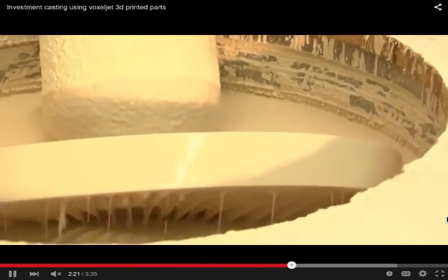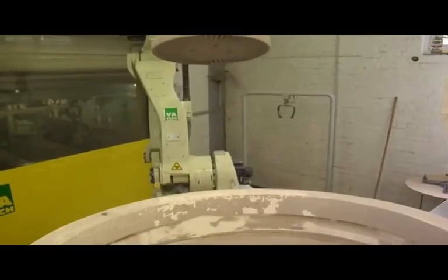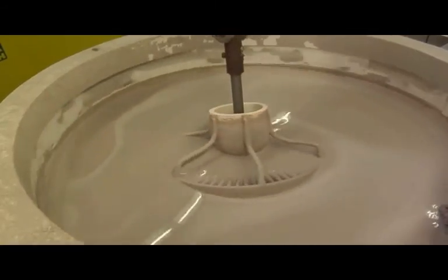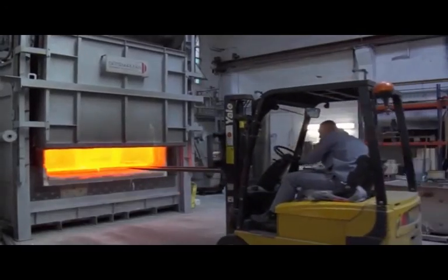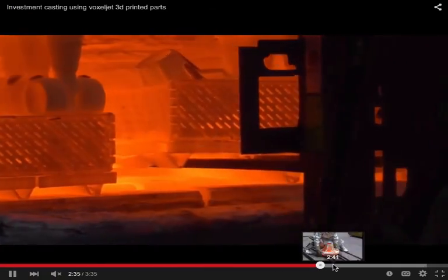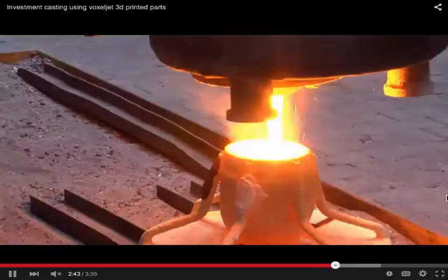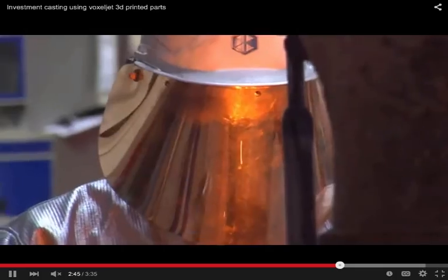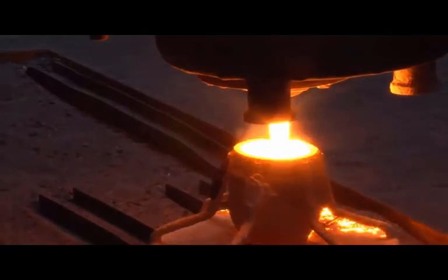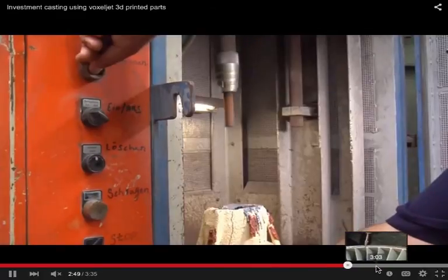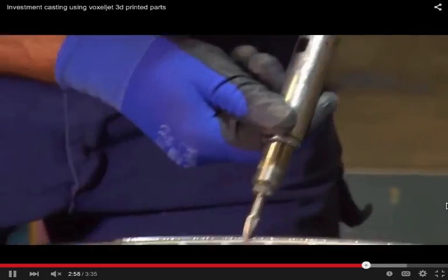They'll do it by hand at first, and then by machine. And once they do that, like I said, they'll burn out the wax. So that's why it's called a lost model, right? They burn out the model they built initially. Then they let it cool, and then they pour some molten hot metal in there. And eventually, you get something that looks nice like this.